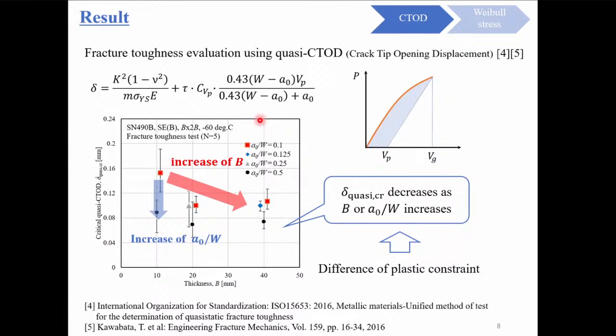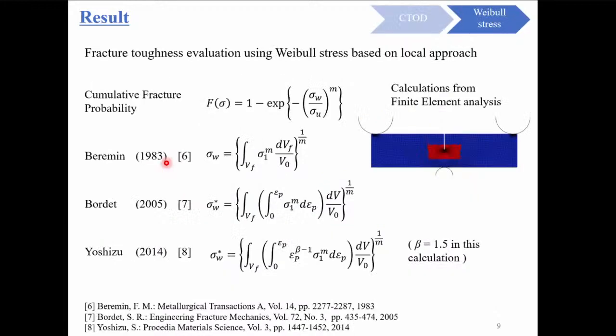First, it was found that the critical quasi-CTOD, which is a fracture toughness value directly obtained from experiments, decreases with increasing plate thickness or notch depth, probably due to the difference in plastic constraint. Next, when the critical Weibull stress was calculated from the finite element analysis based on the local approach,